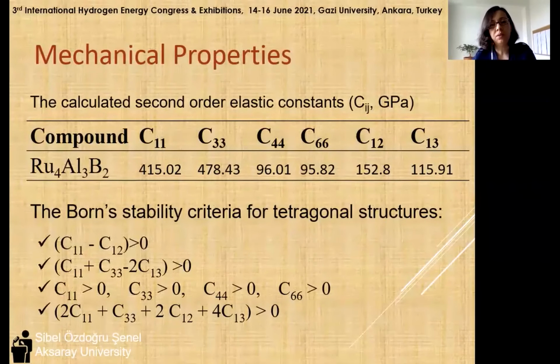The second-order elastic constants of the ruthenium-4 aluminum boride compound were calculated by means of stress-strain methods based on first principle calculations. The calculated second-order elastic constants are given here with the Born stability criteria for tetragonal structure. It has been determined that the ruthenium-4 aluminum boride compound satisfies the stability conditions for tetragonal structures and is mechanically stable.